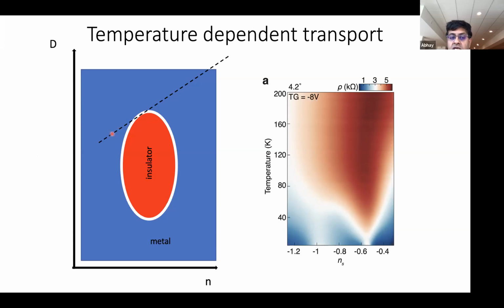And what I'm going to show you is as you tune the density along this particular line, what does the resistance of the sample, the longitudinal resistance, do as a function of density? And if you sit at low temperature, what you'll recognize right down there is the insulating phase at half filling. This is an insulating phase at full filling, which is a simple band insulator. And as you raise the temperature, you'll see that the resistance actually changes quite interestingly as a function of temperature. And perhaps one of the really interesting aspects of this is that at high temperature of about 200 Kelvin, the resistance just saturates, becomes temperature independent.